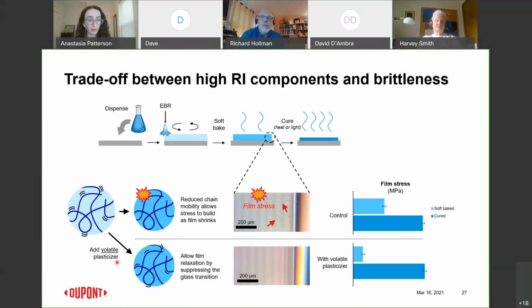So, adding a little bit of volatile plasticizer into the system allows the chains to relax and suppresses that glass transition. So now our image is crack-free. So now our film has none of those cracks that we saw in the previous state, and the film stress that we are trying to lower is greatly reduced in the soft bake. And you can see that the film stress is maintained after the cure to the same number. So, this film stress, as well as a lot of other indicators, tell us that the plasticizer completely leaves the film in the cure process. So we get back the material that we wanted in the first place while fixing this intermediate problem on the way.